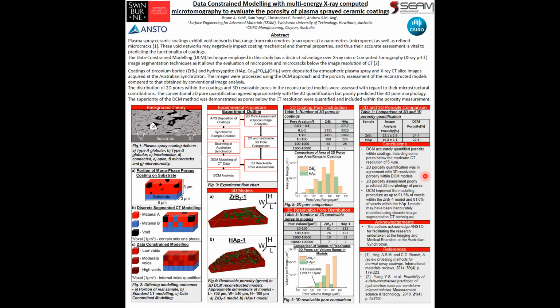from the 2D inspection. Finally, an analysis of the models revealed that the DCM approach improved modelling, with up to 91.5% of voxels within the ZrB2 model and 81% of voxels within the HAP model identified to potentially be incorrectly modelled if typical CT segmentation techniques had been utilised.